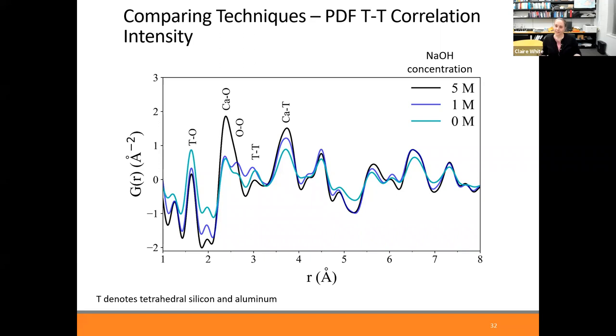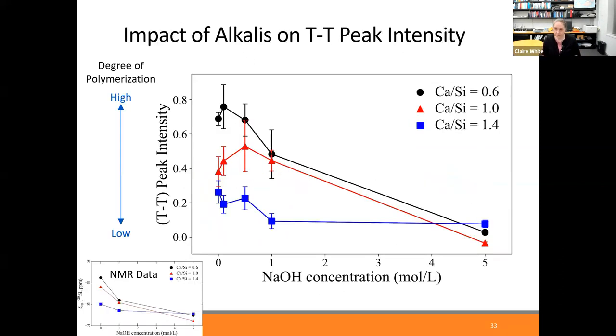What we did for fun was actually to take the intensity, so the Y value of this data here for this local peak, which is related to the distance between silicon-silicon and silicon-aluminium. And so if you have more of these distances that show up, we think it's an indication of the degree of polymerization of the material. And actually what we found when we plotted these intensities is, yes, we end up with a similar plot to the NMR data. This is kind of cool.